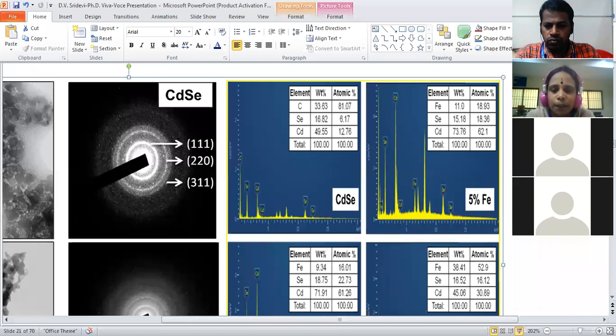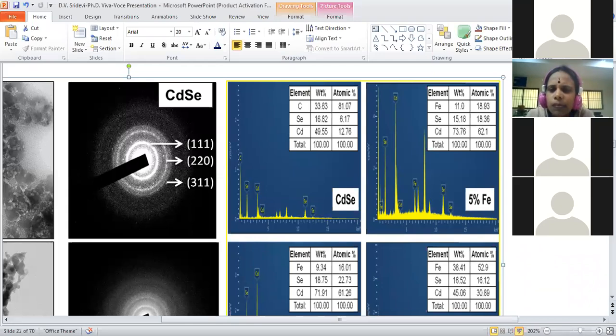See this one, the first one is 5%, and the 10% and 15%. The atomic percent, see there is a variation: for 5%, 18.93%, for 10% it is 16.1. Suddenly there is a drop. So you increased the iron concentration to 10%, it also decreases in atomic percentage. What is the reason? But in the third one, 15%, it increases to 52.9. Have you noticed, and what is the reason?